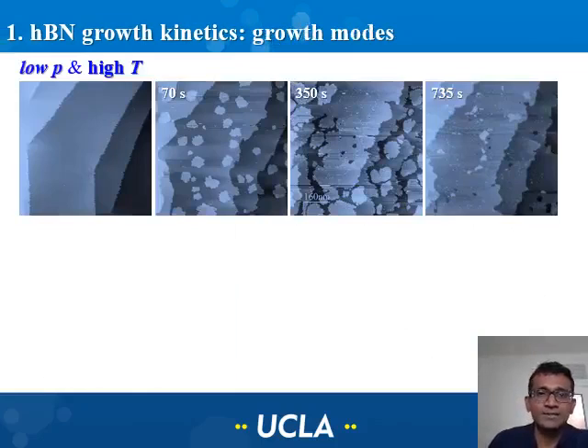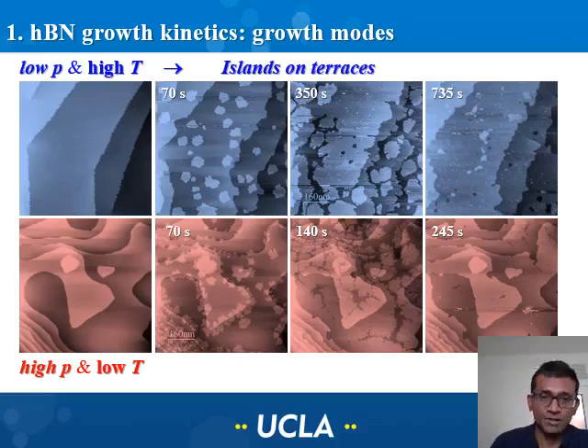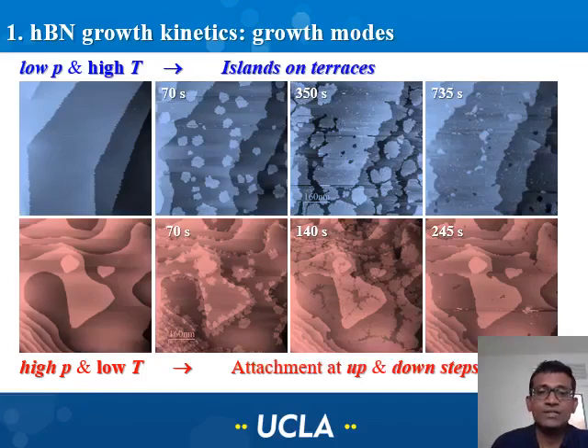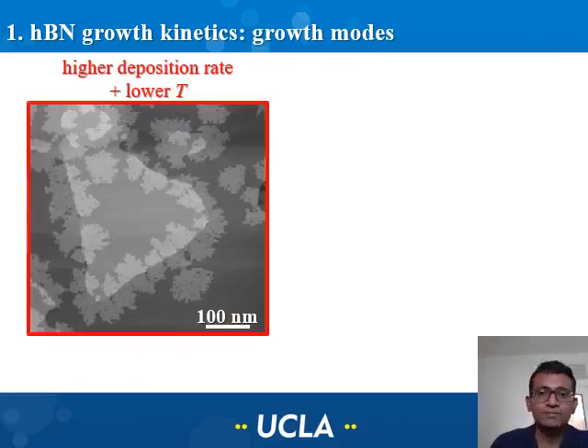And let me highlight the most prominent differences that we observe during these two growth scenarios. When we carry out the depositions at what we call low pressure and high temperature, we observe islands on the terraces before it forms a complete monolayer. In contrast, when we carry out the deposition at higher pressures and lower temperatures compared to the previous run, we observe deposition preferentially at the step edges, both up and down step edges, and eventually we get a complete monolayer. So in both cases, we end up with a complete monolayer of hexagonal boron nitride, but the growth mode is different. I'm going to focus more on these differences in growth modes.